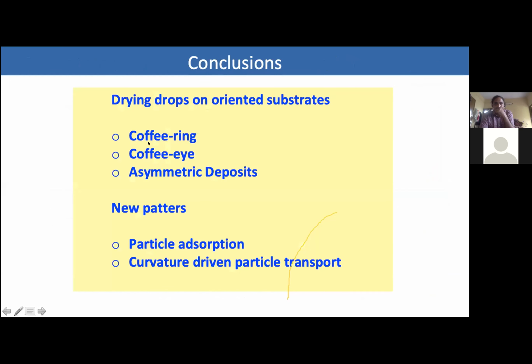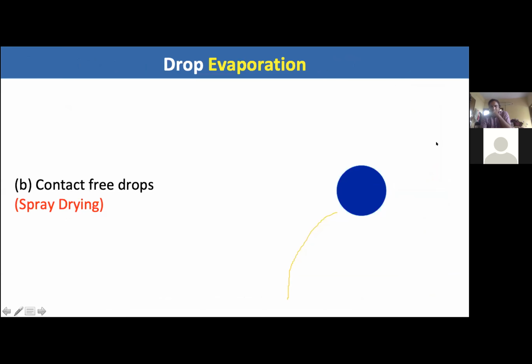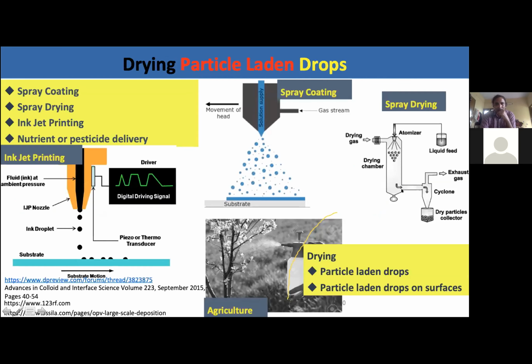So with this in mind, we have been able to show that there's a coffee ring formation when you have drops dried in the sessile mode. There's a coffee eye or asymmetric deposit formation when the drops are dried in other orientation. So in the next 10 minutes or so, I'll talk a little bit about drying of contact free drops, which occurs, for example, in spray drying.